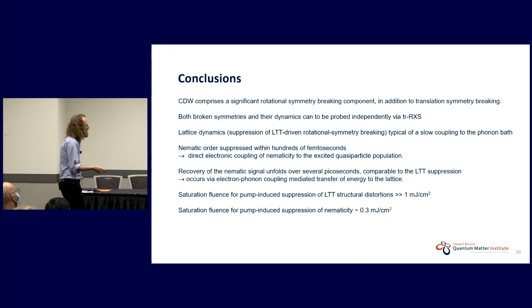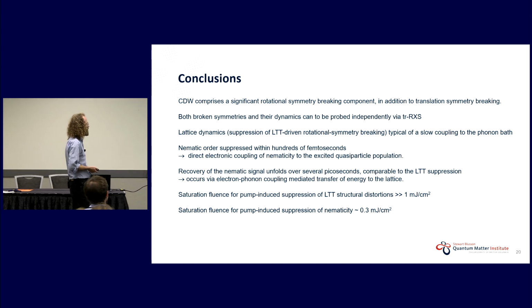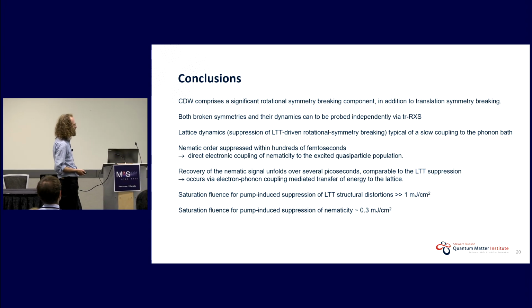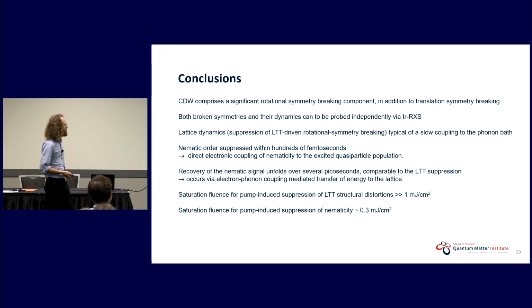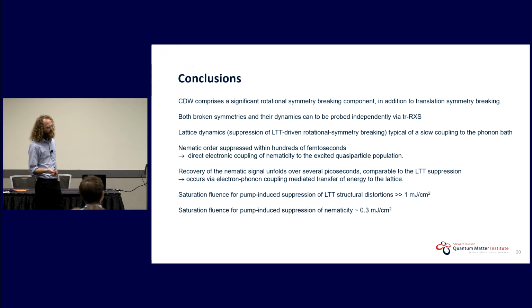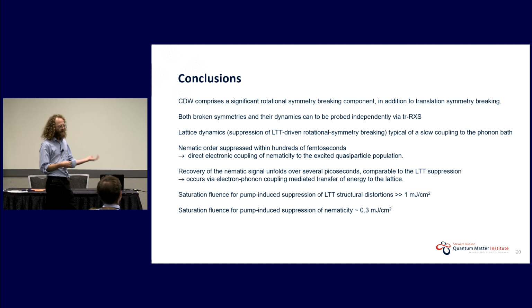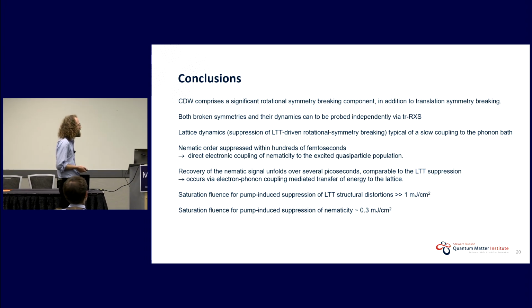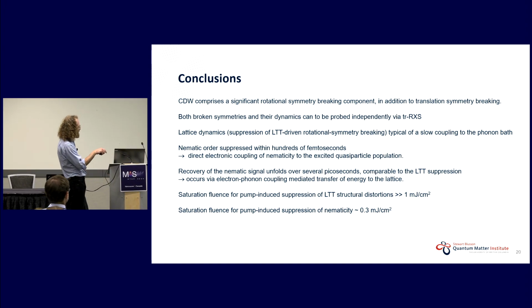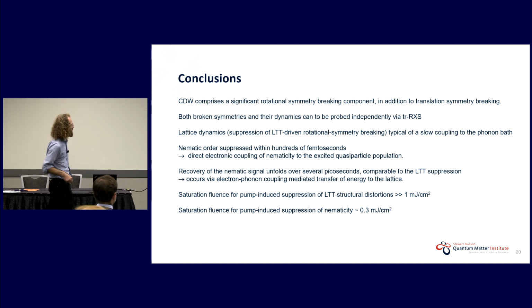CDW, as we already know, in 214 compounds comprises a significant rotational symmetry breaking component. But now we show that we can explicitly probe that, and in particular probe the dynamics of both the translational and the rotational symmetry breaking separately. The lattice dynamics are typical of a slow coupling to the phonon bath.